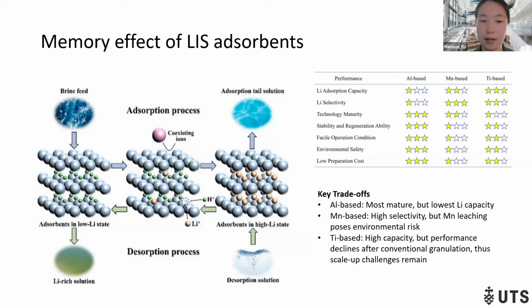And the manganese-based adsorbent has a high selectivity, but the manganese leaching has the risk of damaging the environment. The titanium-based adsorbent has a high capacity, but it is not as fully researched as the other 2 types of adsorbents. And also the performance declined after the conventional granulation, which hindered its scale-up research. So in my research, I chose the titanium-based adsorbent and used it another way in CDI rather than the traditional granulation method for selective lithium recovery.